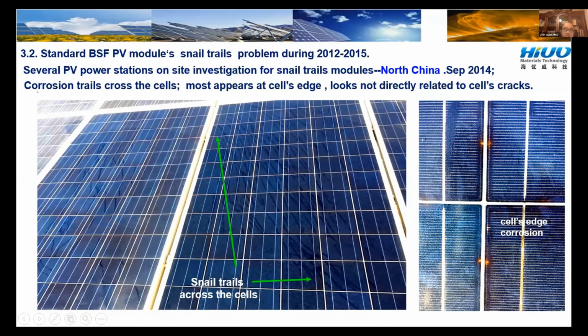We found that the crossing trails across the cells are not related to cracks. You can see here, from top left, this module still has some, but this module looks like this. From here, like a water flow to the right down way, a lot of snail trails cross a lot of cells. And look at this small part here. A lot of crossing along the edge. It's not related to the crack.